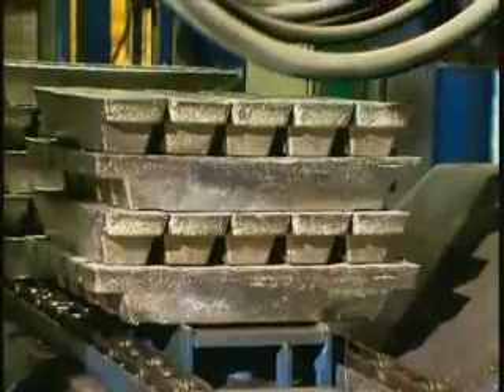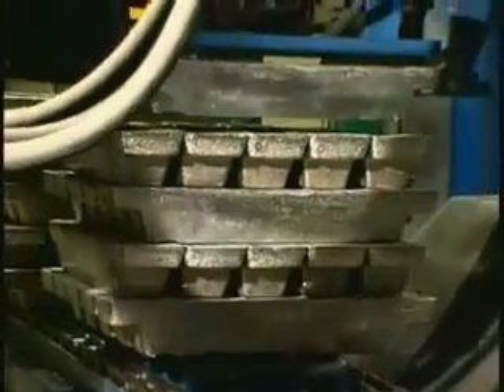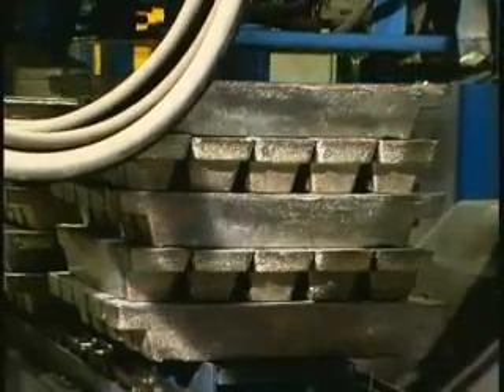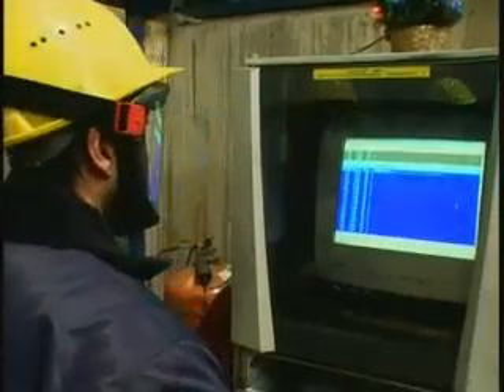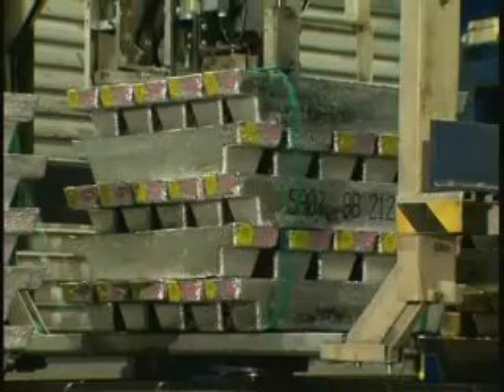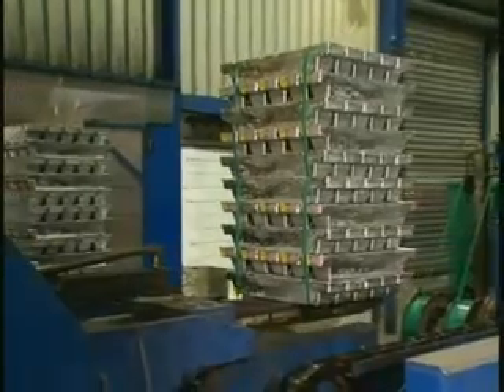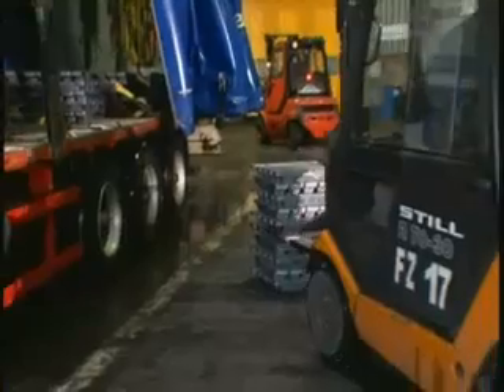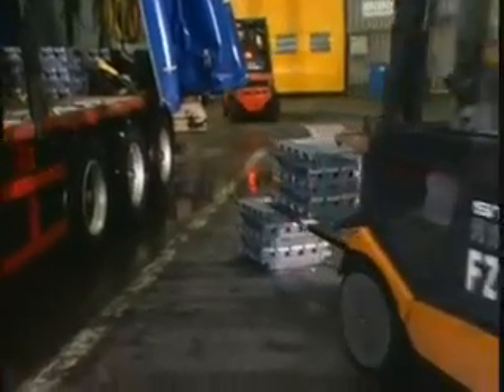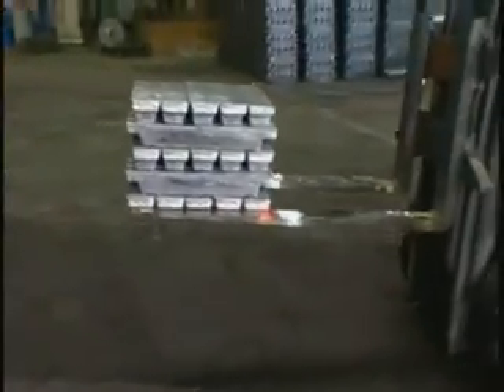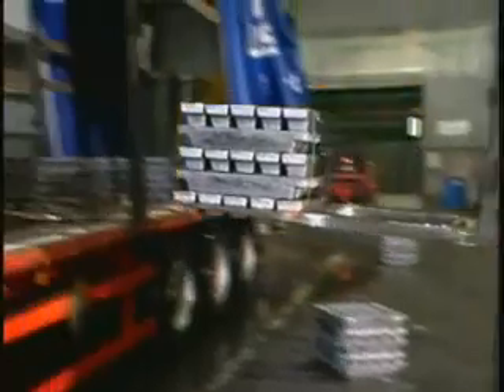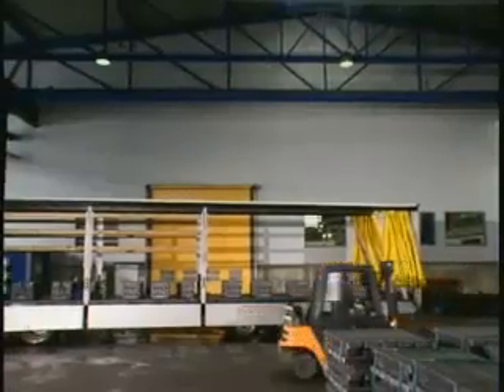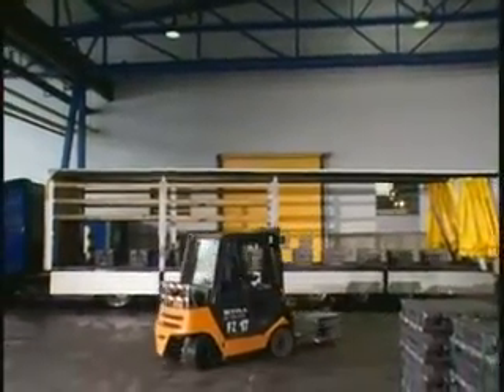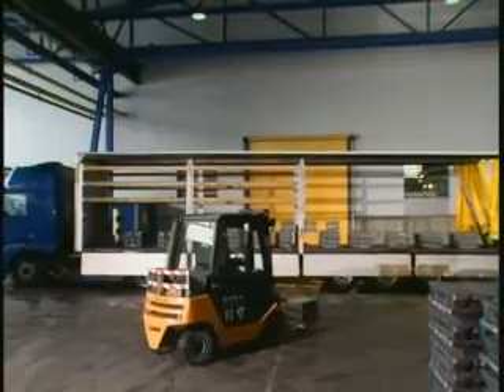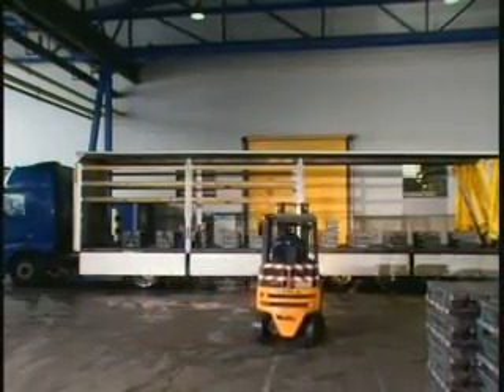Subsequently, the bars are mechanically stacked and weighed. The data are recorded electronically, the stacks marked with numbers, and bundled. Each package stack weighs an impressive 1,250 kilos. Small wonder, therefore, that a truck loaded with 25 tons still looks fairly empty. Year by year, 140,000 tons of lead are delivered to customers. This corresponds to 2.8 million bars.